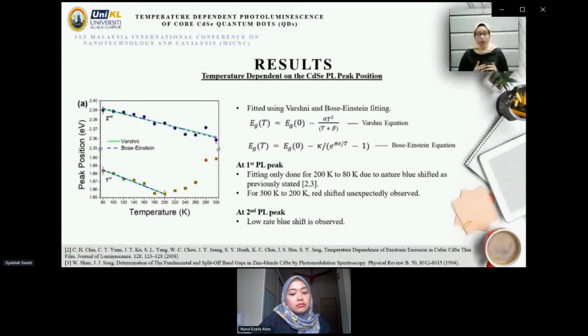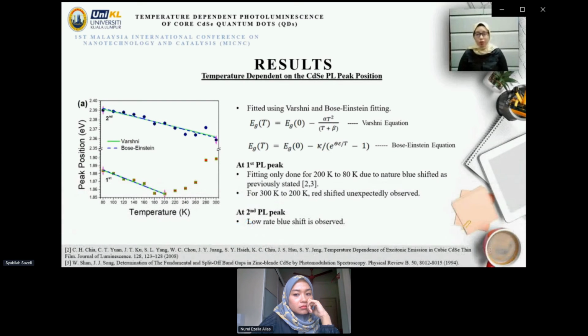The Varshni equation is acknowledged to yield wide variation in thermal parameter for the same material. This indicates the energy gap at 0 Kelvin. This is the temperature coefficient. This parameter is related to the Debye temperature. From the figure, generally, we can observe as temperature increases, the PL peak position decreases. However, at the first PL peak, fitting can only be done at temperature range 200K to 80K due to the nature of blue shift peak position, which is the same as previously reported by others. At 200K to 300K, the redshift behavior is expected due to the increased temperature causing high vibration energy within the quantum dot atoms, and this leads to lower bandgap behavior.